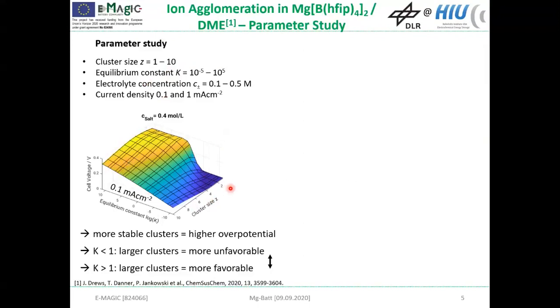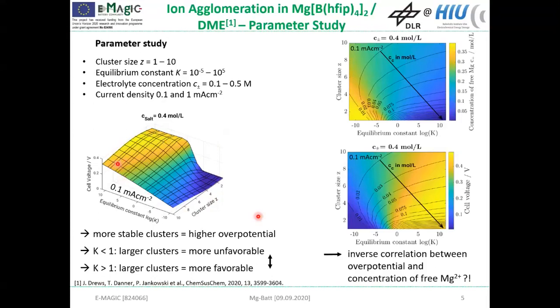Moreover, we can see that when the clusters are thermodynamically unstable, then larger clusters are more unfavorable for the battery performance. And the opposite is true for stable clusters. So here in this case, the larger clusters are more favorable for the overpotential. So when we now compare the influence of K and Z on the cell voltage, which can be seen here as well, and the influence of K and Z on the concentration of free magnesium, we can see that there seems to be an inverse correlation.